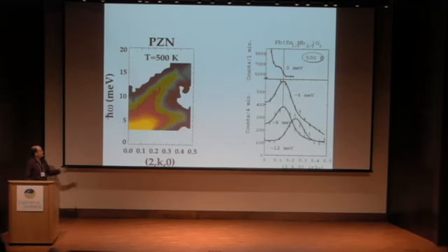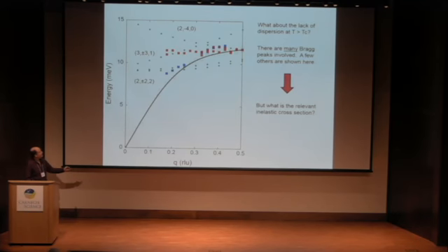Now, finally, the temperature dependence also, you might say, if I go back one slide, here doesn't really follow the extinction. Well, for one thing, it's not the 200 Bragg peak that's involved. That was the factor of 21 that Mike mentioned. This is 2 minus 4, 0. The other thing is there's the phonon Bose factor. That operates in the opposite direction as the release of extinction. Third is there's thermal expansion. Even if it's small, it changes this double scattering condition a lot. Okay? And any kind of change in the phonon line width, et cetera, also will change the intensities.